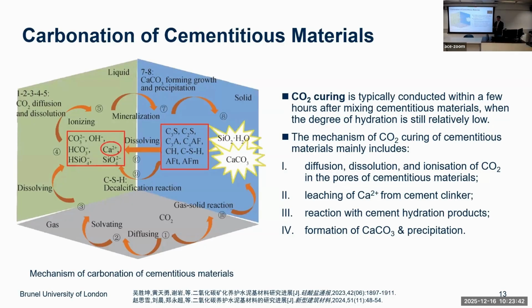Then precipitation. The precipitation could have a side effect. It could prevent further carbonation of other products because it covers uncarbonated cement particles, C-S-H, and we need a solvent. Later on we use some additive to prevent or improve the dispersion of the generated calcium carbonate so that it will not cover the other parts which are unhydrated.